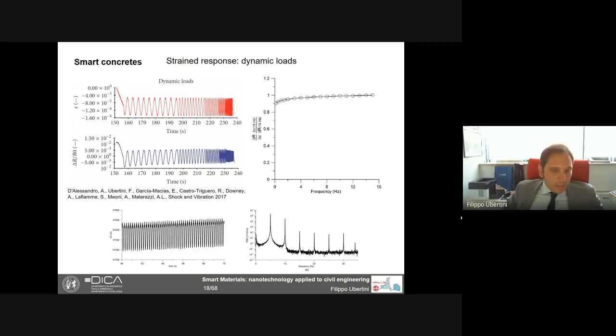What is very nice is that we can also do this in dynamics, so do vibration monitoring with these sensors. We can apply a frequency sweep signal, in red, and you see the response of the sensor in blue. So the sensor can go high in mechanical frequency. And actually, if we look at the frequency response function of the sensor, so the amplitude of the response as a function of the mechanical frequency, we see that these sensors are almost linear.